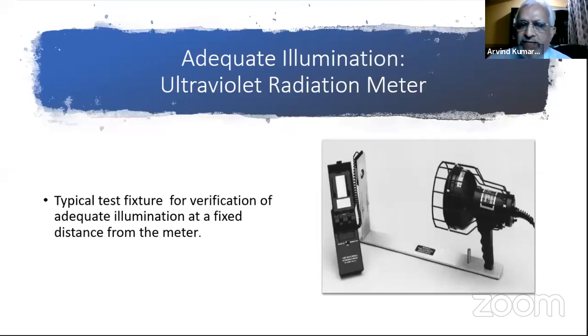And how you do that is, suppose you have a say 30 watt or 40 watt bulb, which is kept at a meter. There you hire a lux meter and check what is the intensity. And if you're getting minimum 1000 lux, then you know that by using a 30 watt bulb at a 1 meter distance, I'm able to get that minimum lighting that is required. So that you have it in your file established, and then you can carry out the PT examination accordingly. You don't have to use the lux meter every time.